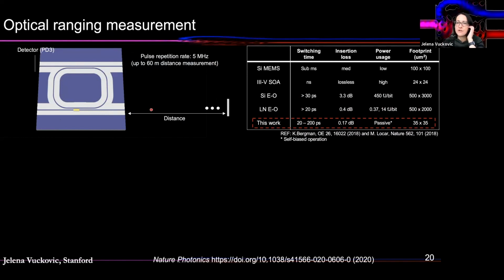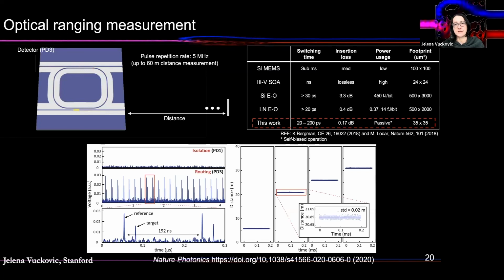And of course, you can use a variety of off-chip switches to do this with very high speed, or you can implement an on-chip isolator, which people have been working on with magneto-optic materials or some dynamically tuned approaches for larger scale photonic systems. But all of these solutions have some issues, either in terms of insertion losses or switching time limitations, and so on. In this case, for this particular application, we can achieve very high operating frequency, so we don't have a switching time issue. The footprint is very small, it's just another two resonators on the silicon chip, and insertion loss is only 0.17 dB. And indeed, we did a 60-meter ranging measurement using this.